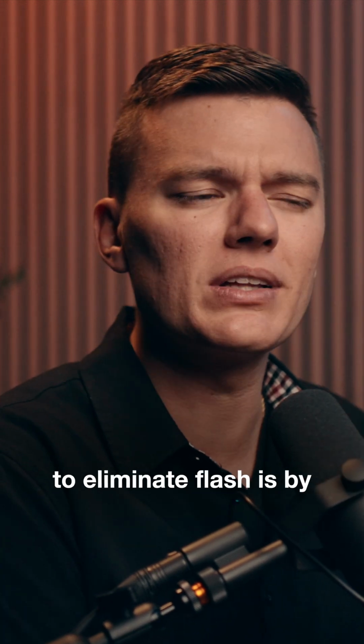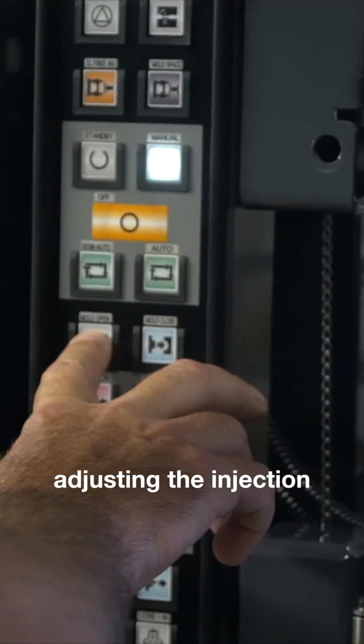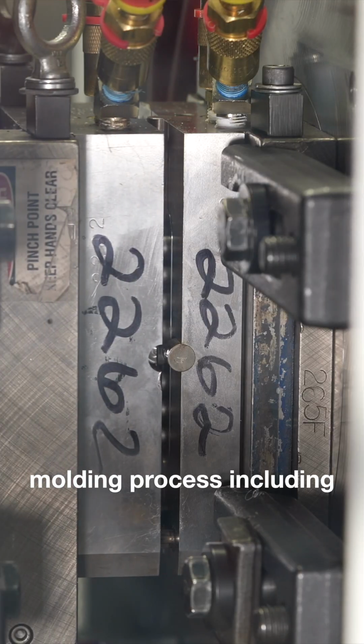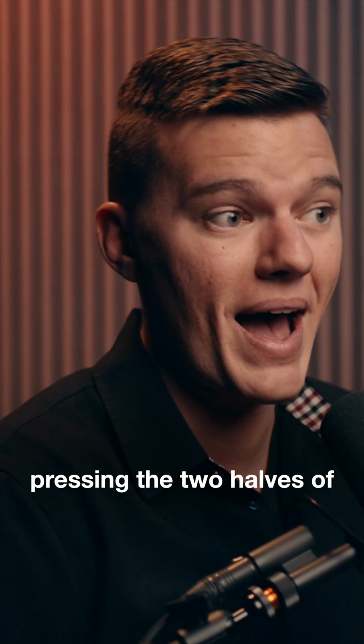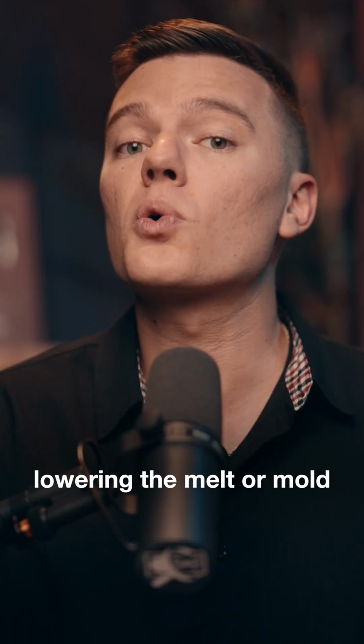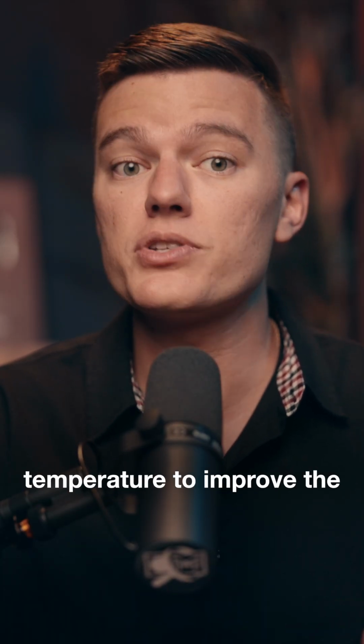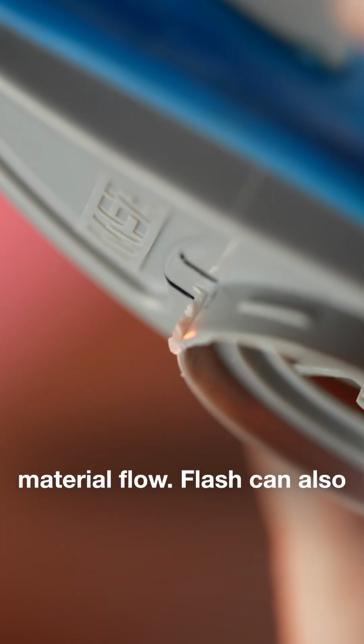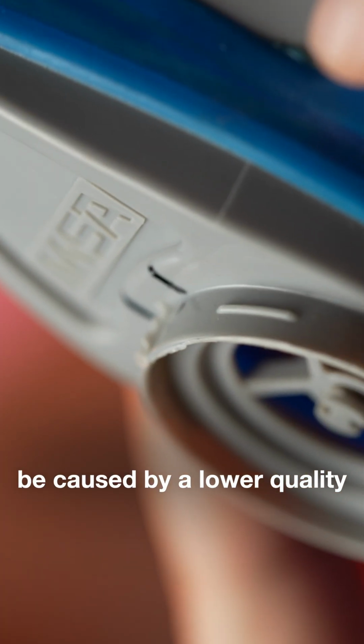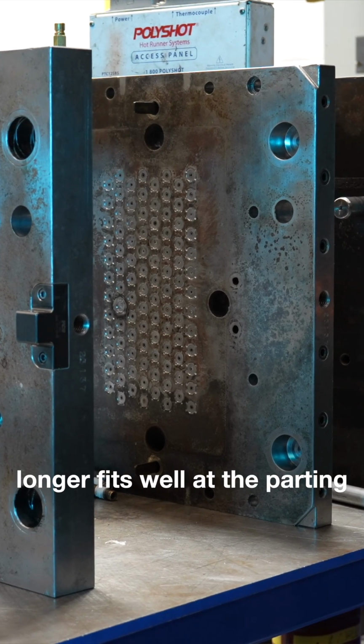So the best way to eliminate flash is by adjusting the injection molding process, including the pressure being used to press the two halves of the mold together, or by lowering the melt or mold temperature to improve the material flow. Flash can also be caused by a lower quality or worn down mold that no longer fits well at